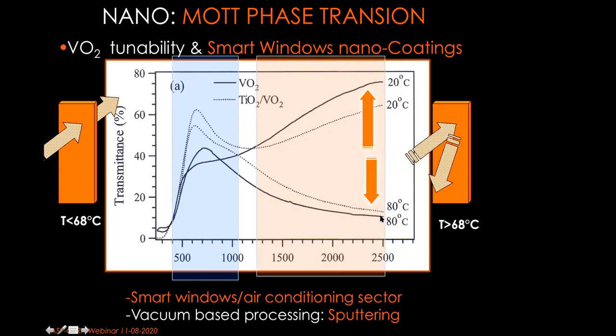As you can see, what does it mean? That means when the thin film on that glass is hot, the film is reflective. It does not allow the infrared to come in. It's opaque to the infrared. That means that this film stops the infrared when it's hot. That means that if you are in your car and your car is coated with this VO2 at 20 degrees Celsius, if the temperature outside the car is less than 20 degrees Celsius, which means it's cold, the heat, the infrared from the sun are transmitted through the window to the inside of your car.